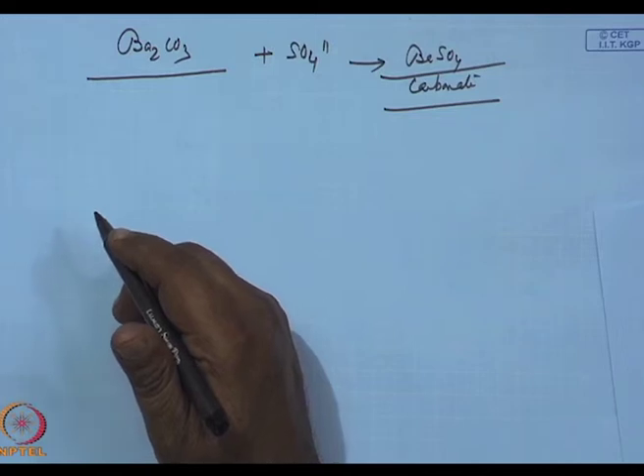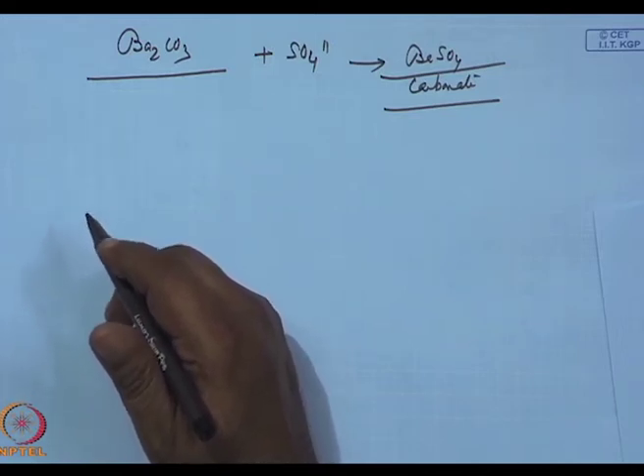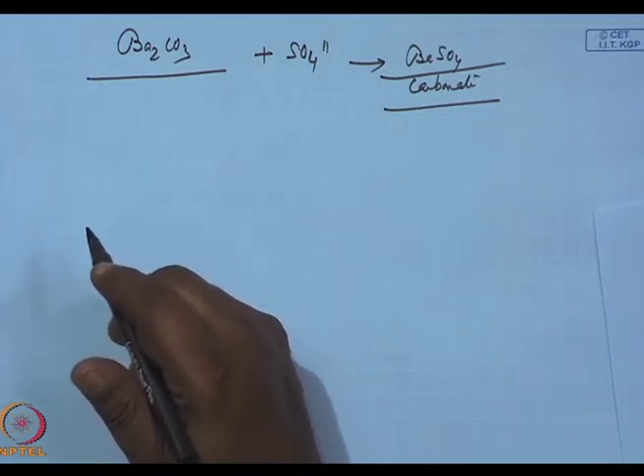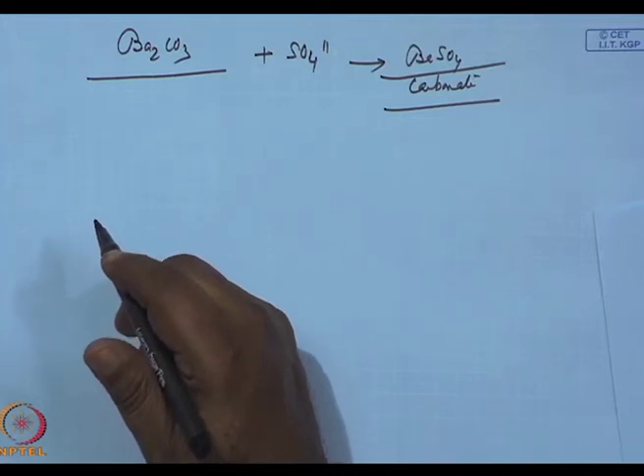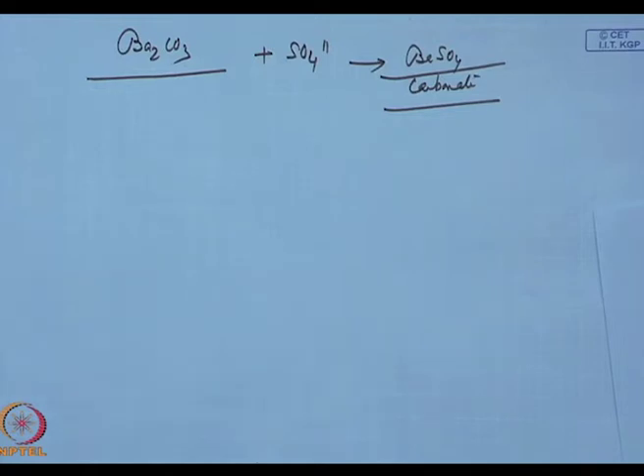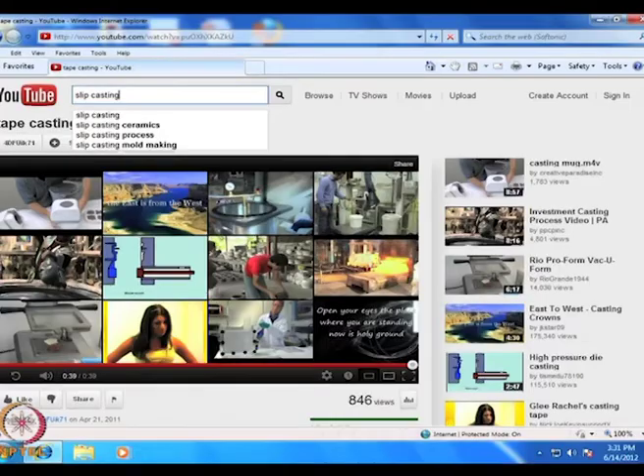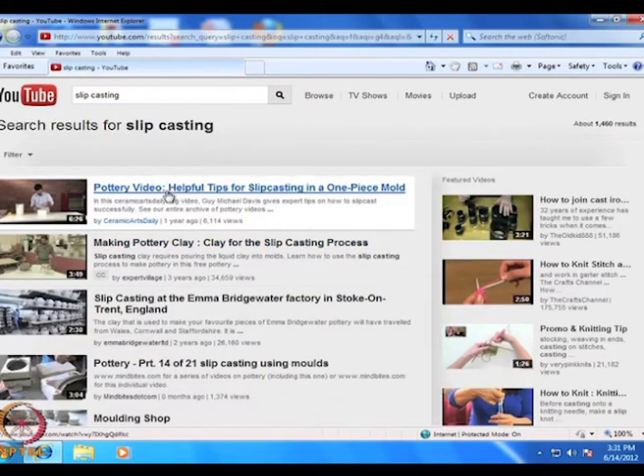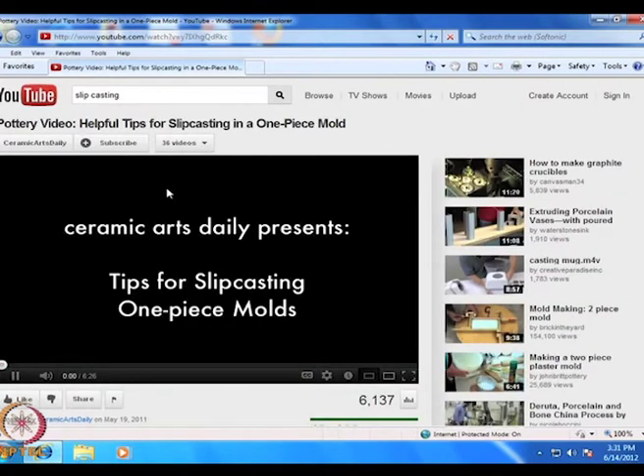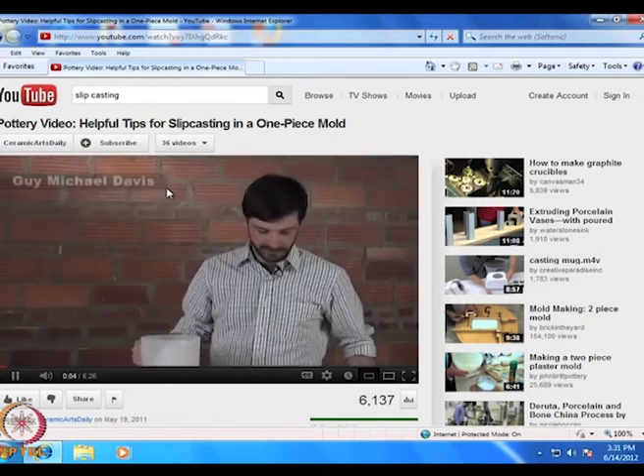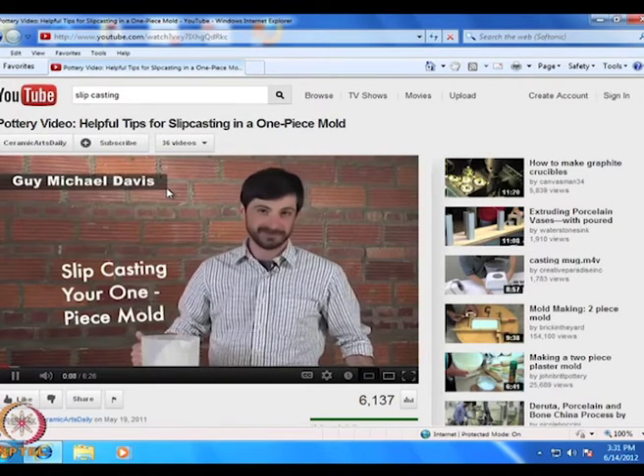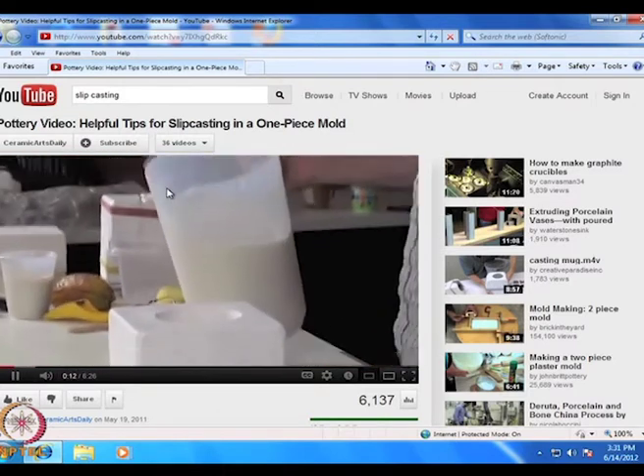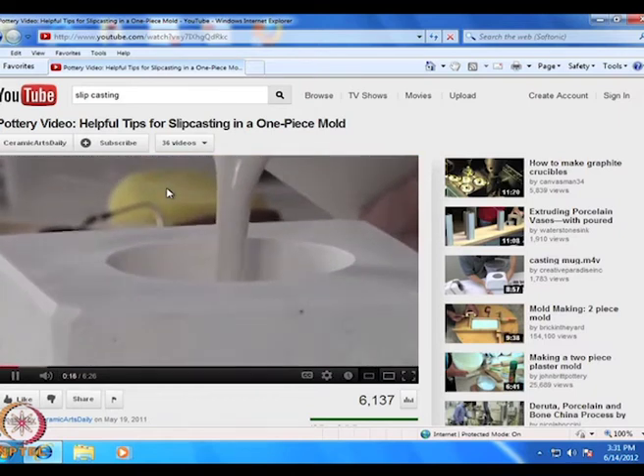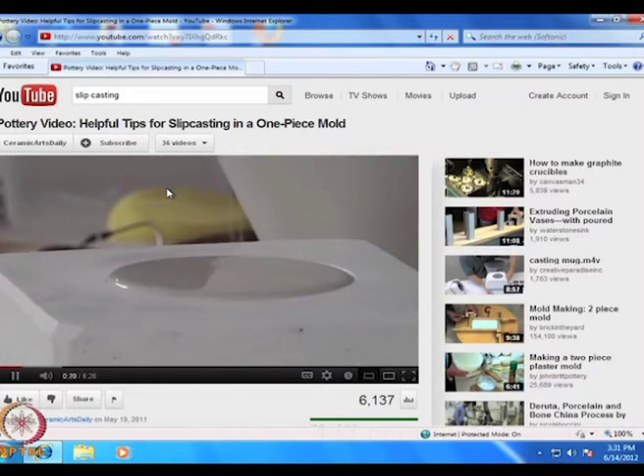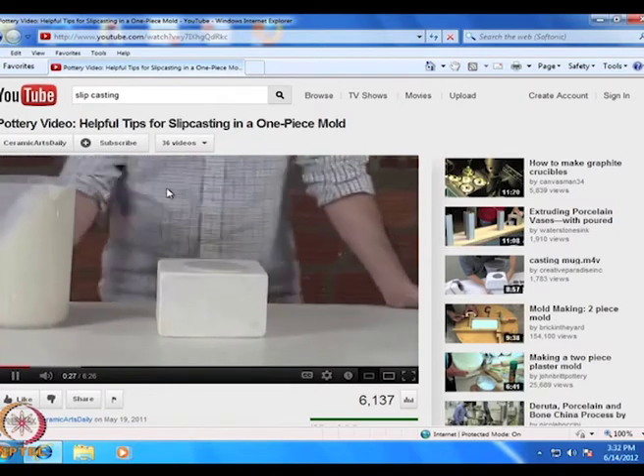There are other deflocculants also which are used, even tripolyphosphates are used, and barium carbonate I have already said. A lot of these are used. In each case, if you remember, I have to prepare a slurry. This is a good video, and this says what are the tips for casting the slurry of the mold. What the gentleman does here is he pours the slurry into the mold. You can still see the slurry is quite thick, and the slurry is pouring over.